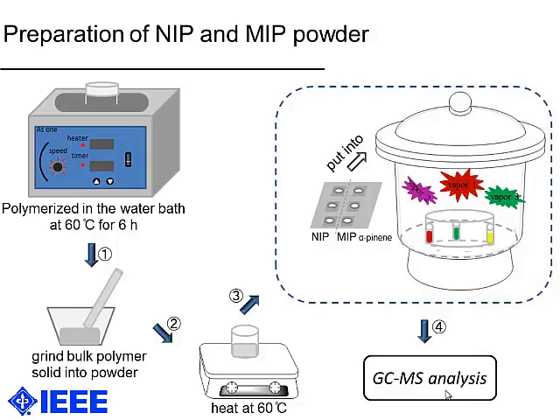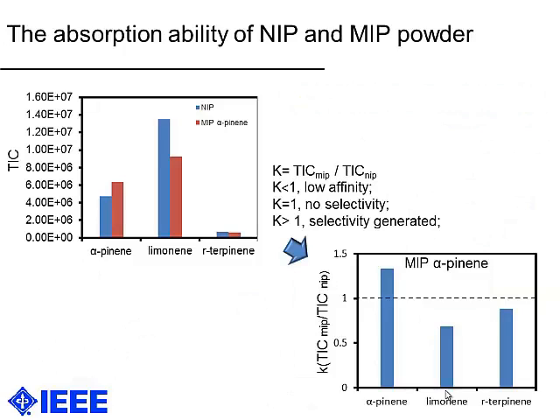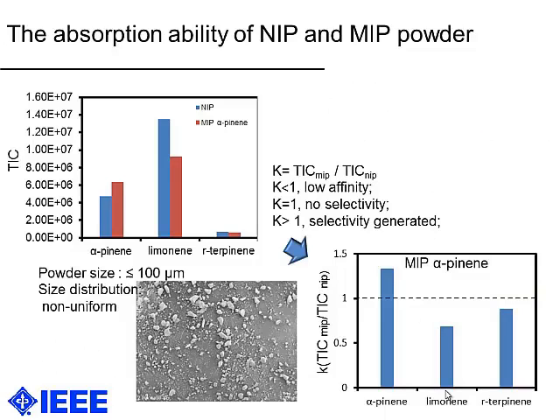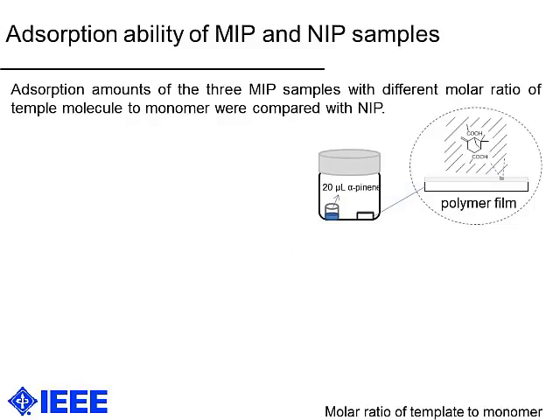Last part will be the GC-MS instrumental analysis process. And this is the absorptivity compared between NIP and MIP powders. It's shown like this one. Here we can see that the absorption ability of MIP powder is higher than NIP powder. And also here we use a constant K, which equals this. And we think that when K is lower than 1, that means low affinity. If K equals 1, there is no selectivity. If K is larger than 1, that means selectivity is generated here. And also from this graph, we see that the terpene vapor imprinted polymer has a certain selectivity generated in the imprinting process. And then according to the result, we made the polymer films on glass substrate.